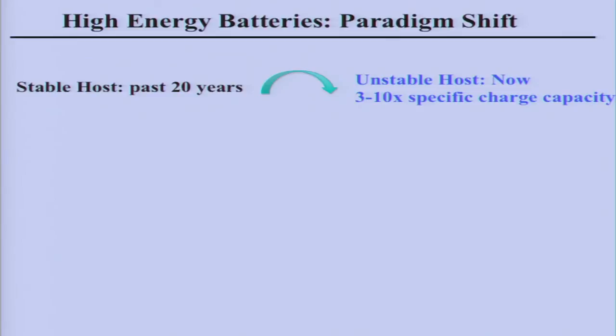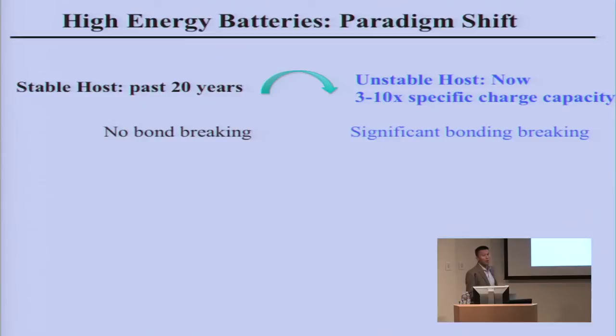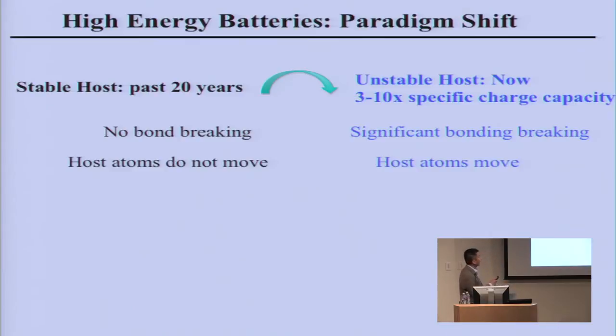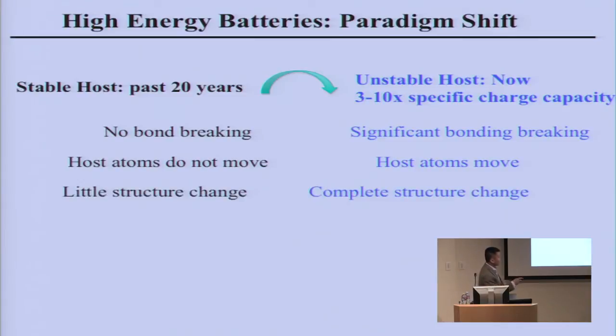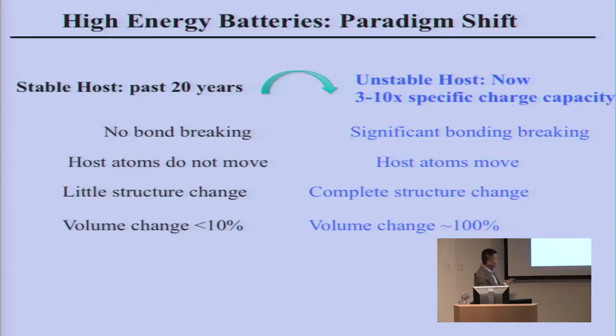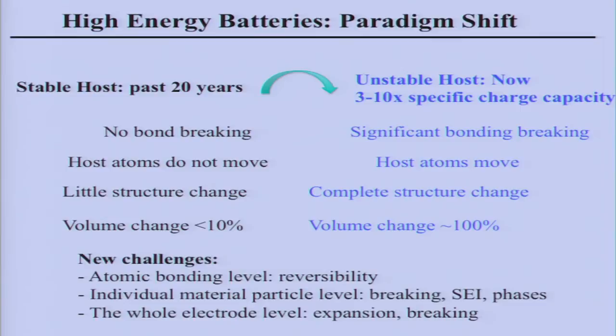Coming down to the science question: in the past 20 years, what we learned is we need a stable host. There's no chemical bond breaking to store lithium through intercalation. But the new materials require a paradigm shift, because chemical bonds will be broken when lithium and electrons come in. Host atoms do not move; now host atoms move over very long distances. Small structure change becomes complete structure change, and small volume expansion becomes 10 times more volume expansion in these materials. So the challenge we are facing is to completely redesign the whole battery, from the materials level all the way up to the electrode level and the whole battery cell level.